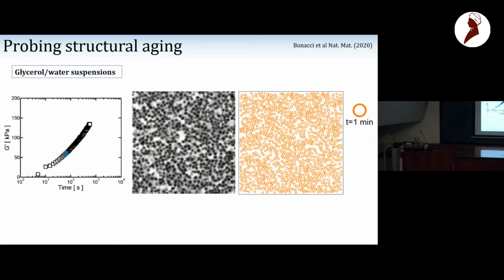So, okay, let's look at structural aging. So we take our suspension, we put it in a confocal microscope. It's a bit difficult because it's opaque, so we need to reduce the index contrast to be able to see the particles. So for that we used glycerol, and so we managed to image. So yeah, it works again. Okay, so that's a photograph. That's the reconstruction of the particle positions.